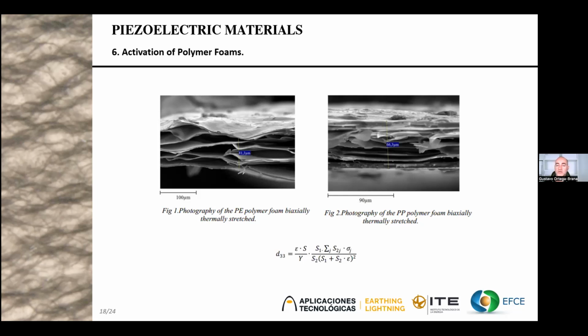The thermal stretching was a bit complicated, and we made this process in 4 steps, and we reduced the Young modulus by one order of magnitude. But the problem with this thermal stretching is that we also reduce the air and polymer percentage to around 60%. But all this is compensated, and the d33 coefficient is higher than before.